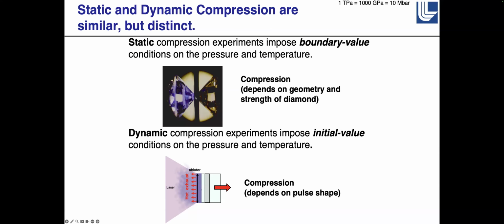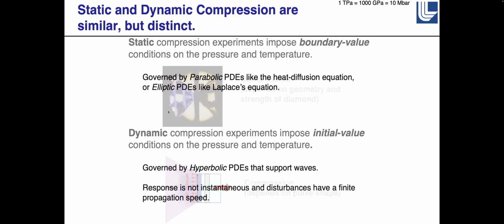container, and that raises the pressure, but it'll stay there for a long time as long as you keep those boundary values on. Dynamic compression imposes initial value conditions, and so we're essentially driving either with a gas gun and a flyer plate, or with a laser ablating a material at time equals 0. We put a very large pressure on our material, but then it has to transit through the sample.